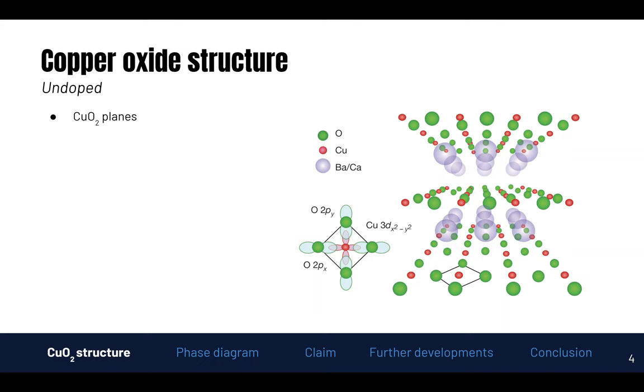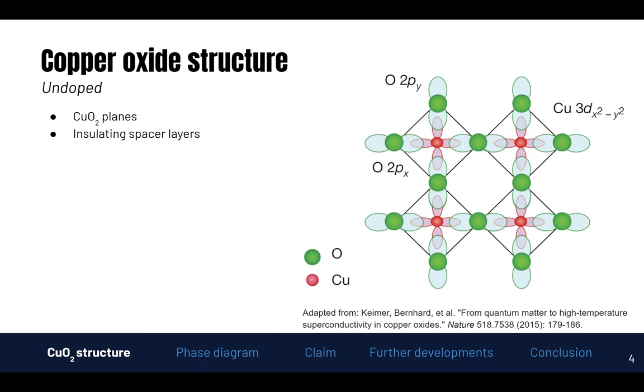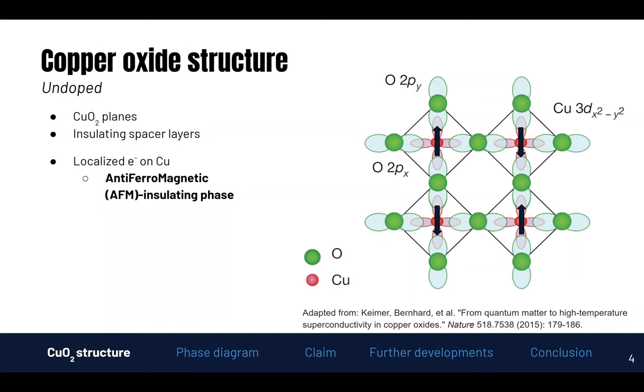So let's start with the copper oxide structure. The general structure for copper oxides is that we have vertically layered copper oxide planes, indicated here with green and red, and then in between we have insulating spacer layers. These spacer layers usually just donate an electron or a hole to the copper plane. Now if we zoom in on these copper oxide planes, we see that we have strongly localized electrons on the copper oxides, and these pair antiferromagnetically due to superexchange of the oxygen atoms.